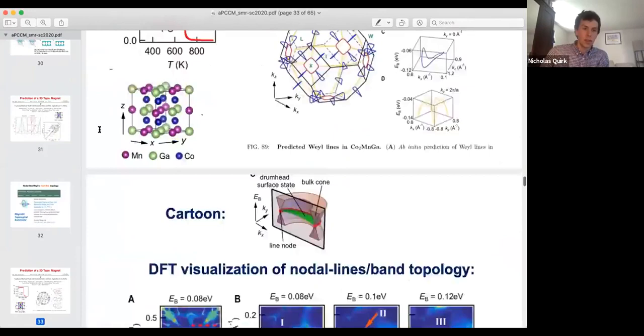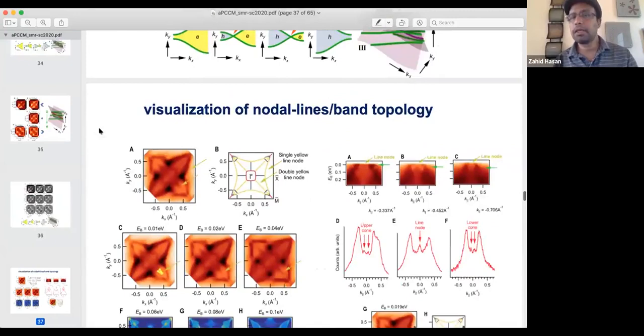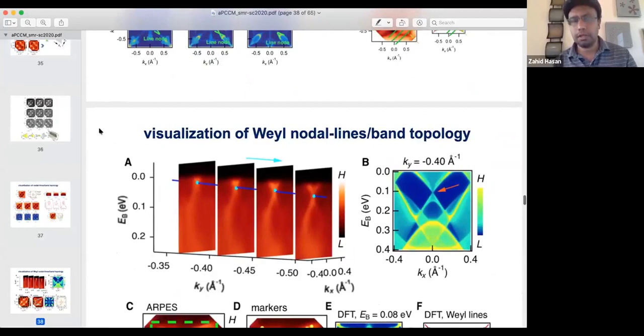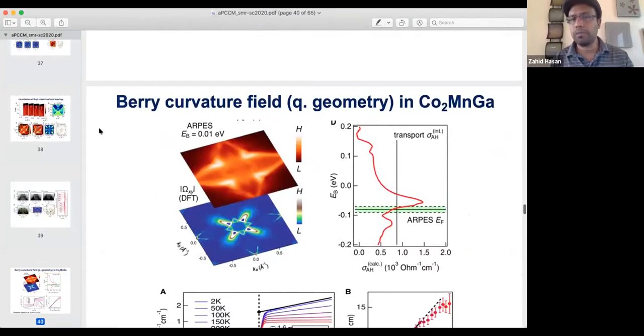We believe that, at least at our operating temperature, from an experimental point of view, it's a Weyl loop or nodal line. But I do not rule out that at lower temperature, where many people have done their transport and talk about Weyl nodes, the loop will break into nodes. So for that reason, I would like to caution transport people that from a spectroscopic point of view, we don't have a way to tell. It's not only us, no other ARPES group, if they claim it, I will not believe them, although nobody has claimed that they're seeing Weyl nodes in this compound.